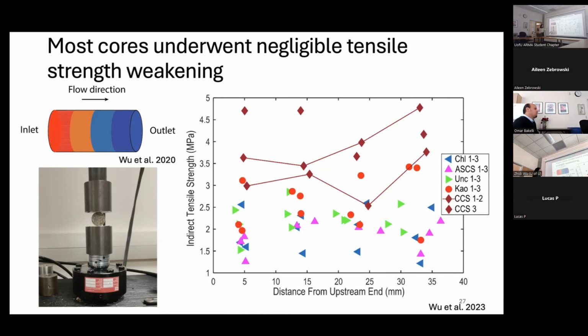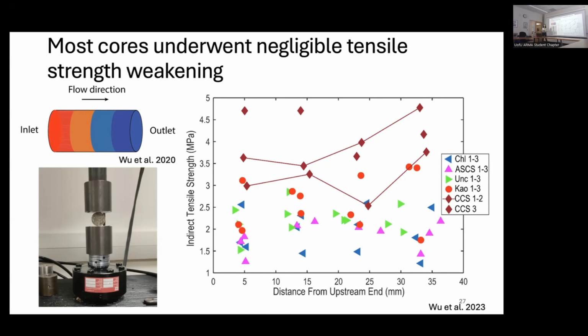So how is tensile strength impacted during CO2 injection? Mostly, I'd say the changes are negligible. We don't see much change, except these data points, the red points connected by those solid lines. Here it's lower on the upstream and higher on the downstream. And they're all generally lower than the control samples, and these two are the control samples. At least in the upstream part of the core, tensile strength appeared to be much lower. That's the only significant decrease in tensile strength that we see. All the other locations of the samples show almost no tensile strength weakening.